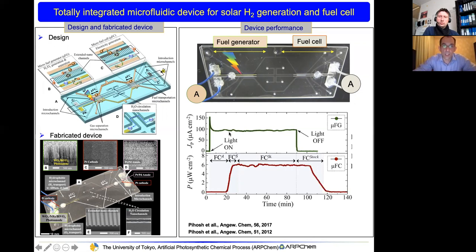Okay, then we need about 20 minutes to generate enough gas to reach the fuel cell, and then, as you can see here, the power started to increase. This is the activation of the fuel cell. It requires about 10 minutes for stabilization. And then, with continuous irradiation of the device, the fuel cell produced electricity of around 6 microwatt per centimeter square. And then at around 90 minutes, we stopped the irradiation.